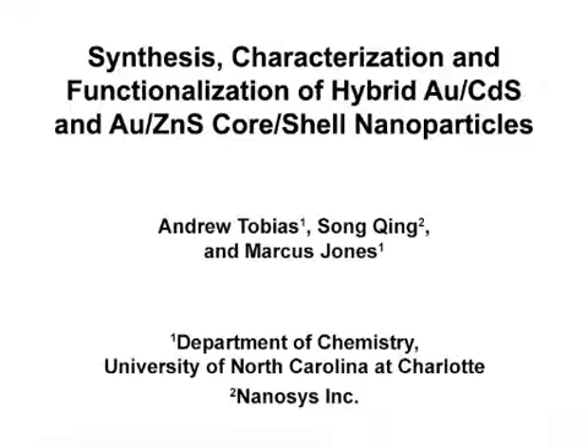The overall goal of this procedure is to prepare gold nanoparticles that are overcoated with a wide bandgap semiconductor shell. The shell material can be either cadmium or zinc sulfide, and the thickness should be tunable.